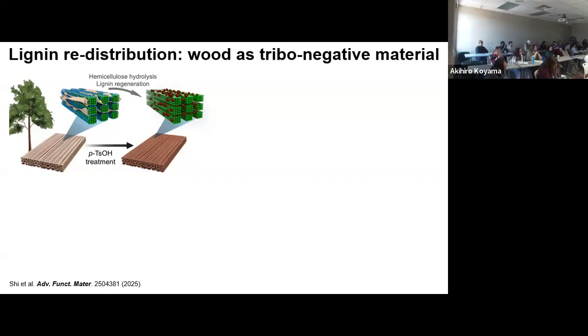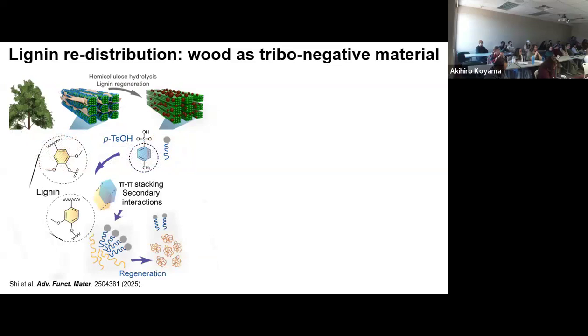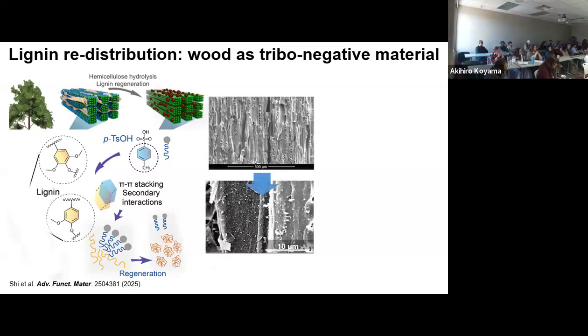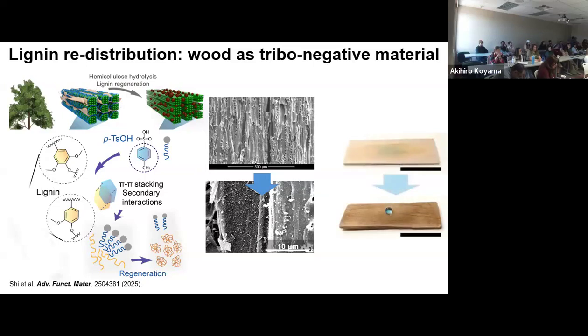You have two things, surface energy and topology. The two help to produce very highly super hydrophobic materials. That's what I show here next. But essentially, that's what we have. Upon regeneration by removal of the solvent and then drying, it's possible to go from here to here. And what you notice here are a lot of lignin particles decorating the material. So we're not removing the lignin, we're keeping it. It's just restructuring the lignin.